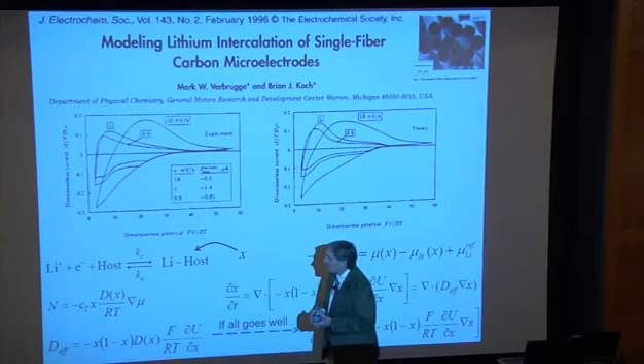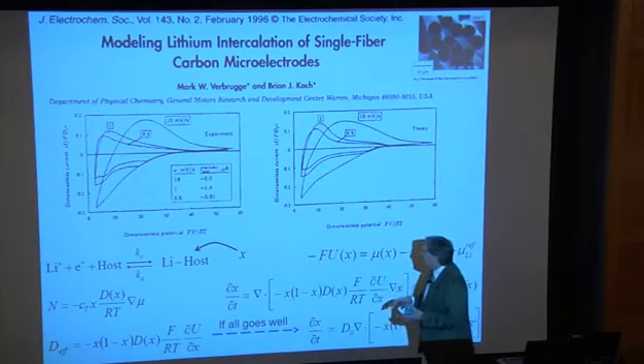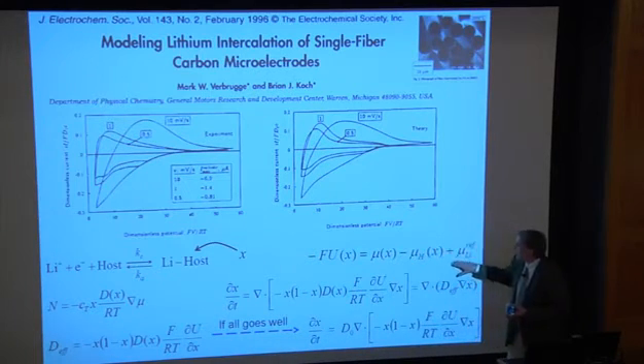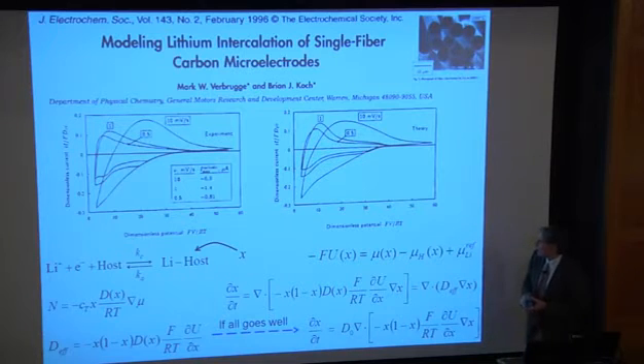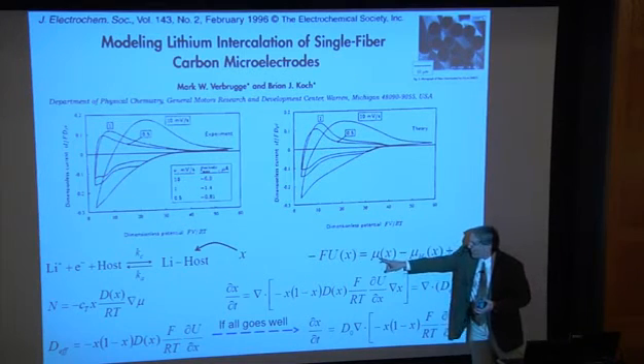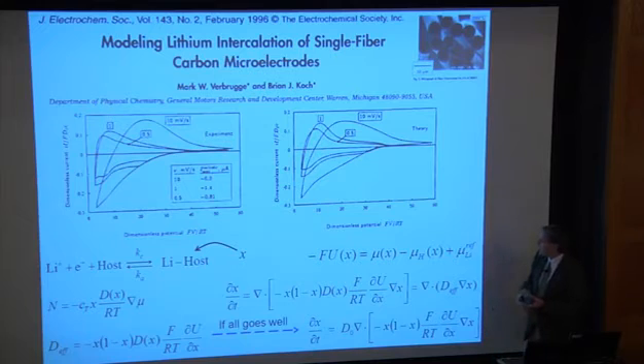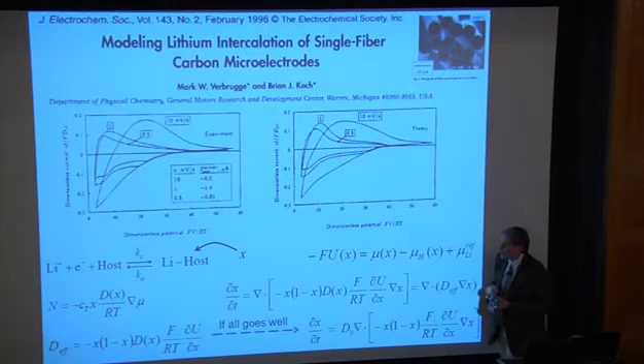The lithium comes up, reacts with the host, and inserts. From the open circuit potential, you can actually deduce the chemical potential of lithium. And so if it's unsubscripted here, no subscript means it's referring to the lithium species. This is lithium in the reference electrode. So in this case, it's the metallic lithium electrode.